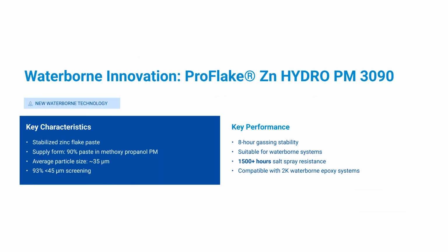In addition to solvent-borne systems, Eckhart has also developed zinc flake technology for modern waterborne coatings. ProFlake Zinc Hydro PM 3090 is a stabilized zinc flake paste specifically designed for waterborne epoxy systems, the first of its kind. The product offers excellent gassing stability, maintaining performance for 8 hours in the systems tested in-house, while also demonstrating compatibility with 2-component waterborne epoxy formulations and corrosion resistance exceeding 1,500 hours in salt spray testing. This development supports the ongoing industry transition toward lower VOC and more sustainable coating technologies.